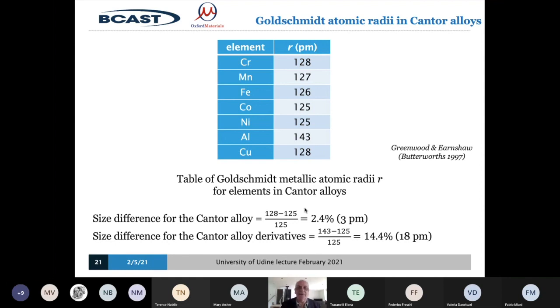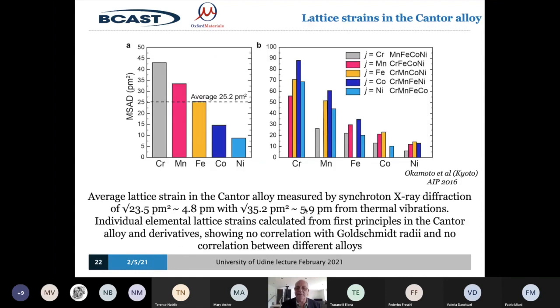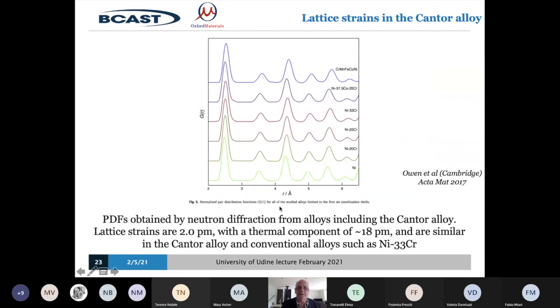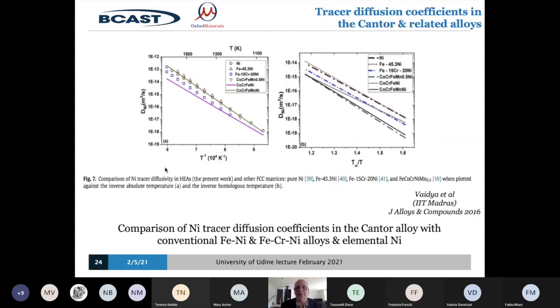This is proved here by some synchrotron X-ray diffraction experiments, which came up with the answer of 4.8 picometers size variations in the material, and neutron diffraction experiments, which showed 2 picometers. So roughly it's in agreement with what we would calculate by a rather naive calculation I've just given you. Well, this leads to 2 important property effects, at least, among many others, but I'm going to show you 2.